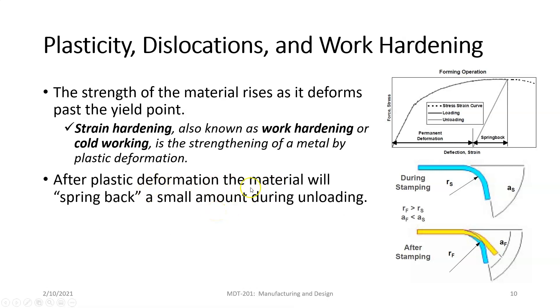After plastic deformation there's going to be a slight spring back. You can find the spring back by taking the slope of the Young's modulus line and applying it at the point where you stop applying the load, then going backwards — and that's how much spring back, measured in strain. So we can calculate the spring back.